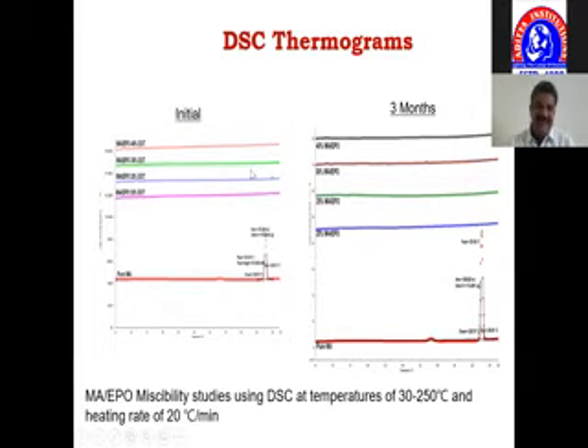These same extrudates were kept at various conditions in the stability studies. After 3 months, there was no reconversion of the amorphous material back to crystalline material. Again, that has been tested by a DSC curve after 3 months. So at this point, you're not able to see, at 230 degrees, any drug melting point.